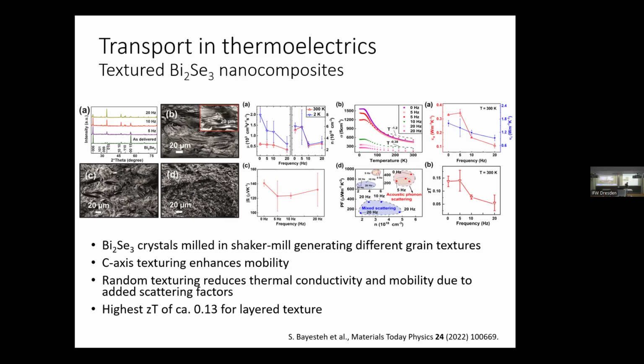That has as a consequence that the resistance changed significantly. Not so much the carrier density, there's minimal change, a factor of 3 or something like that, but the conductivity changes. Of course, we studied what would be the relevant parameters of that: scattering factors, temperature exponents at high temperatures. For the layer structure, the main scattering factor is electron-phonon interaction, pretty normal. For the others, you have more intense scattering, so a more intense power factor than would be the case for only electron-phonon scattering. So you have additional impedance due to the orientation of the grains.